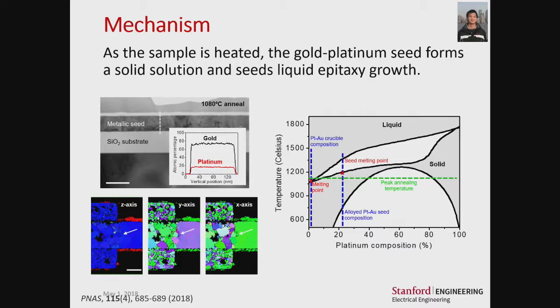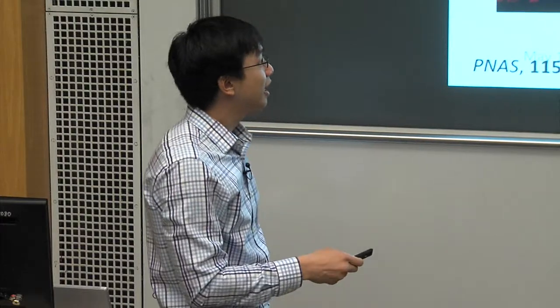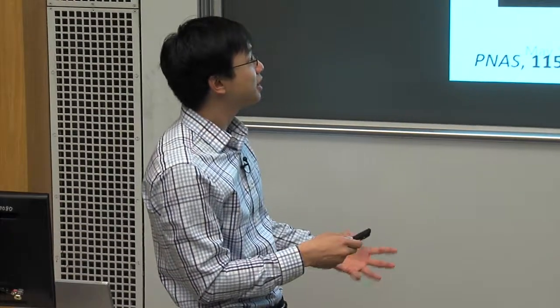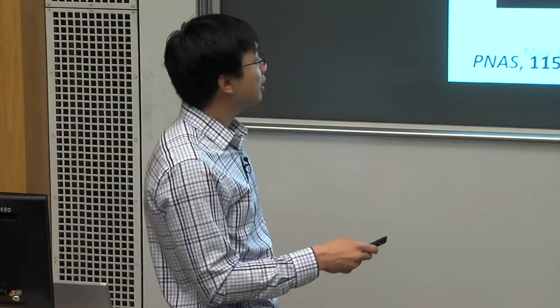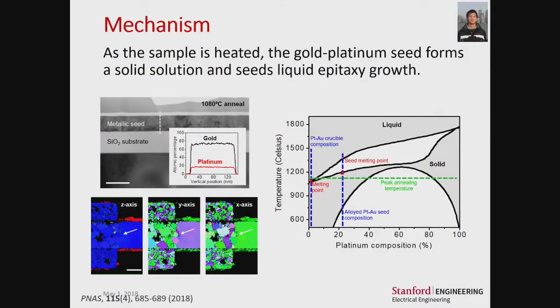And it's essential in this case that the platinum and gold have such similar lattice constants that they produce this eye-like binary phase diagram, and that the lattice spacing of this solid solution is very similar to gold, which allows the liquid phase epitaxy to even work. And we believe that with this understanding of the mechanism, we can generalize this concept to other types of electronically and optically relevant materials, such as silver, copper, and aluminum. And that's something we're actively working on right now.